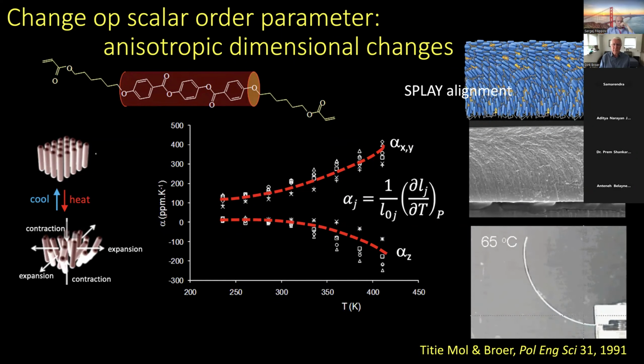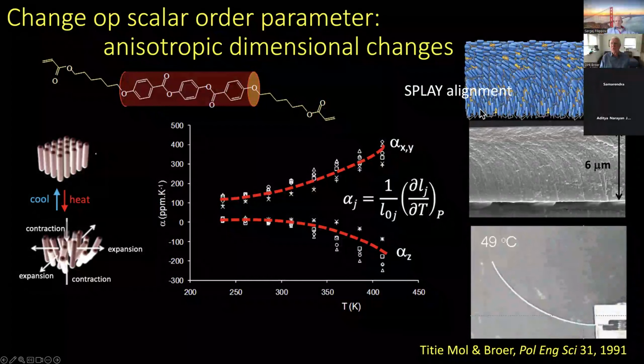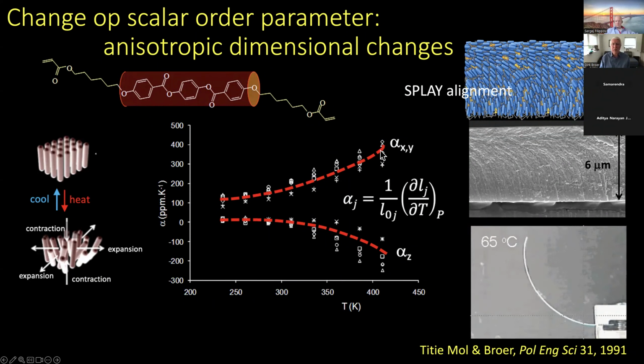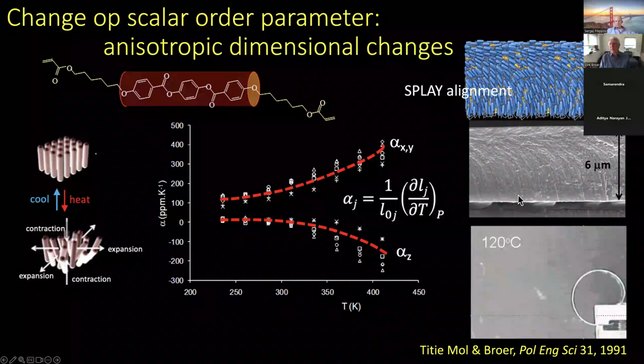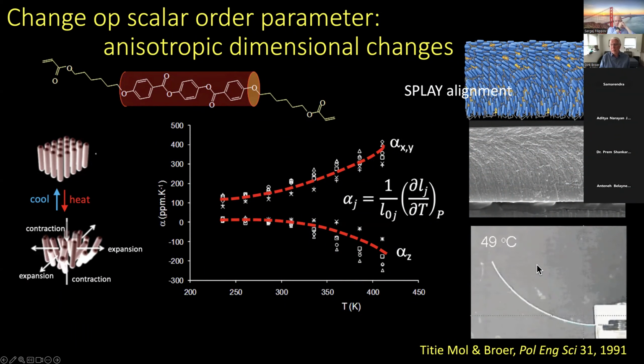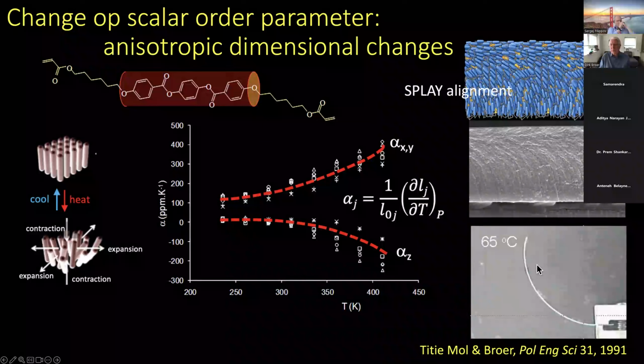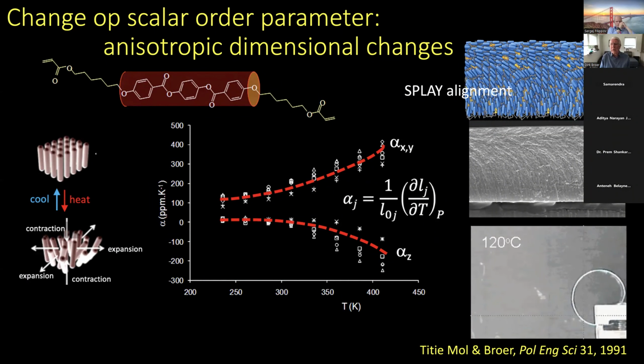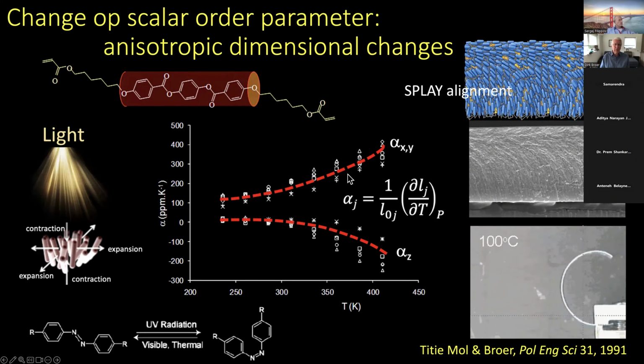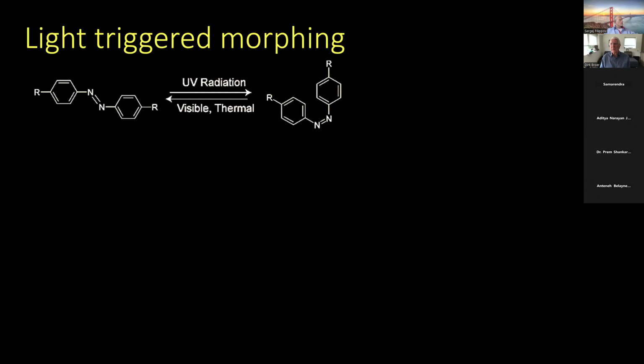Well, then you can already imagine that if you make a film like that and heat it, you will have contraction according to this line at the top, and you will have expansion according to this line at the bottom. So the film has to start bending, just like a bimetal would bend. But of course, this is a monolithic material with a gradual change in the director over the thickness of the film. This is by heat, but you can also do it by light, for instance. And light-triggered morphing, well, the most